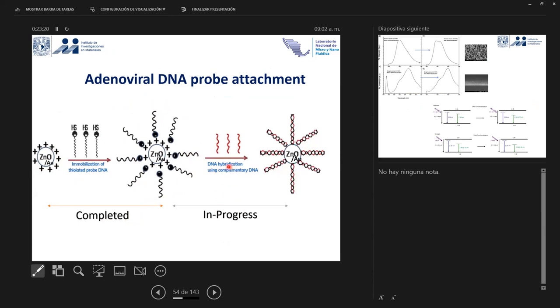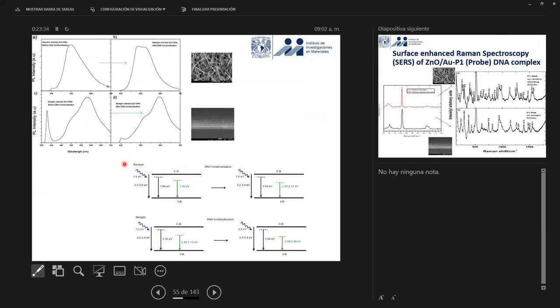Now we are doing the DNA hybridization using complementary DNA, and we want to see the final results for the whole device. In this particular part, I'm just going to show the results of this one interaction of the thiolated DNA with the nanowires. In the photoluminescence technique, these are the random nanowires, these are the vertical nanowires, and this is the photoluminescence spectra before the interaction. They have some differences, but the main peak is around 500 to 600, 700 nanometers. But after interaction, you can see this photoluminescence changed.